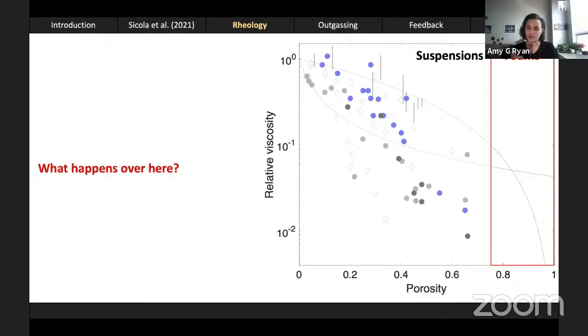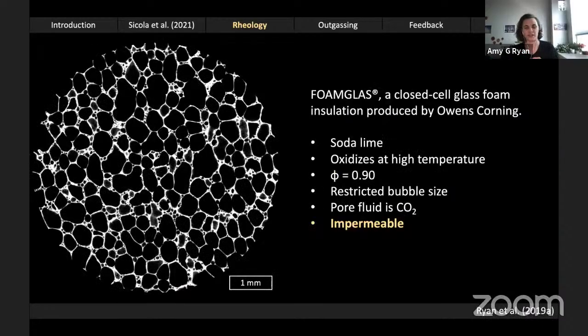In order to conduct experiments here, though, I needed a closed cell glass or melt foam to work with. And luckily, that's something that's actually industrially produced. So for my experimental work here, I used a closed cell glass insulation called foam glass, which is produced by Owens Corning. The solid component of this insulation is a soda lime glass that contains a little bit of iron in it. So it actually oxidizes when exposed to the atmosphere at high temperature. The initial porosity of this material is 90%, and it has a relatively restricted bubble size, as you can see from the XCT image here on the left.